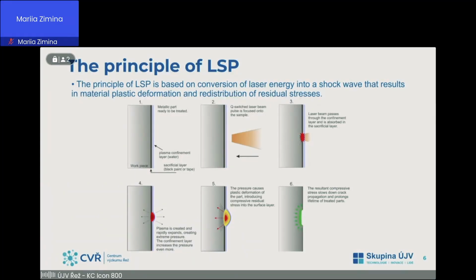Then, after the interaction, the plasma is created and rapidly expands, creating extreme pressure. The pressure must be higher than the dynamic yield strength of the treated material. It's important. And then the confinement layer increases the pressure even more. It's like a shield. Then the pressure causes plastic deformation of the part, introducing compressive residual stress into the surface layer, and we have better fatigue properties and higher hardness and so on.